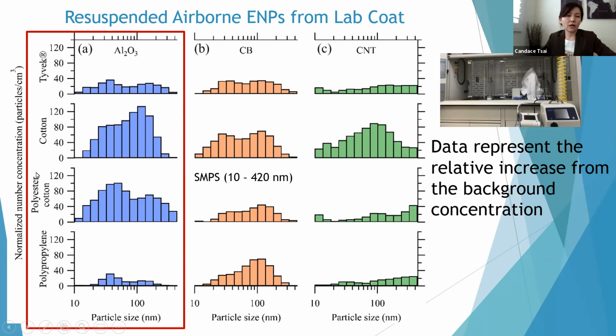We can see the cotton and polyester cotton come up with the highest level of release of nanoparticles from the fabric. We also found cotton and polyester cotton release not just nanoparticles, they also release some fibers.